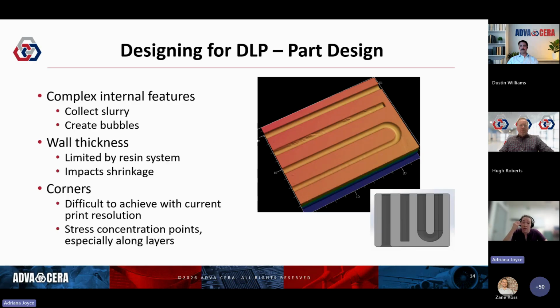Another design consideration is corners and angled features. The print resolution that we're working with is between 31 and 40 micron pixels. This is just a limitation of the printers themselves. That's the DLP set that we're working with. But another factor is that sharp corners are a stress concentration point for any brittle material like ceramics, but especially with the layer-wise buildup of the part during the printing process, if that layer transition and that layer interface aligns with a sharp corner, the stress is extra concentrated and it can cause delamination. But all of those challenges don't mean that we can't print great parts that include those features.